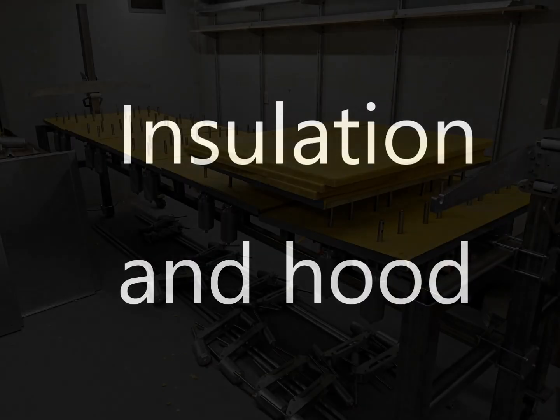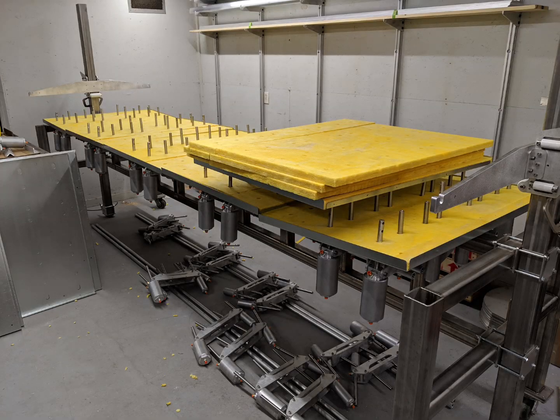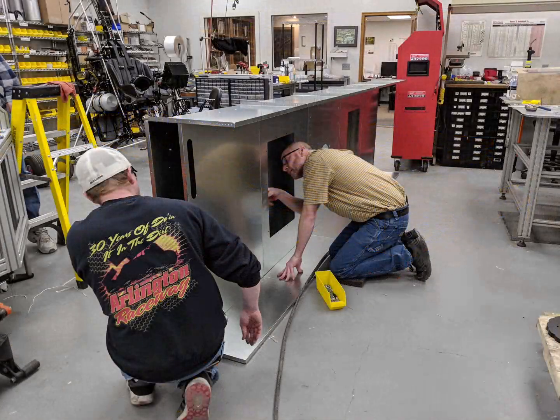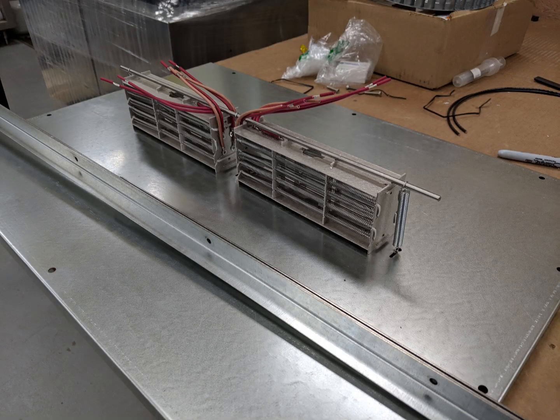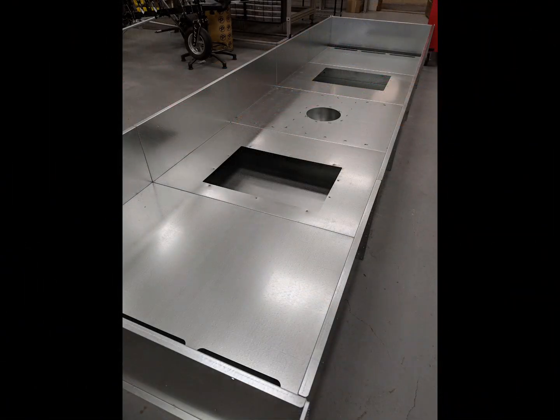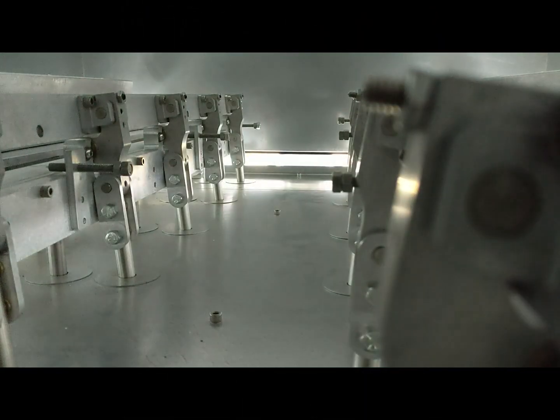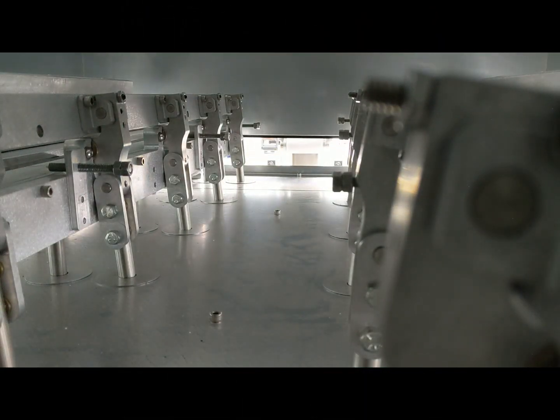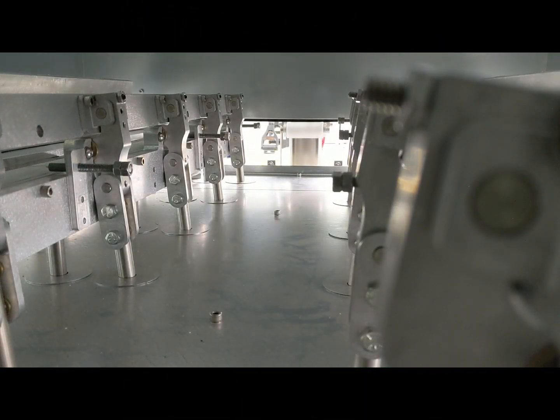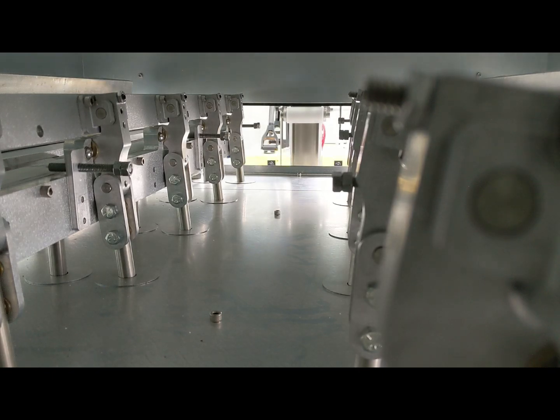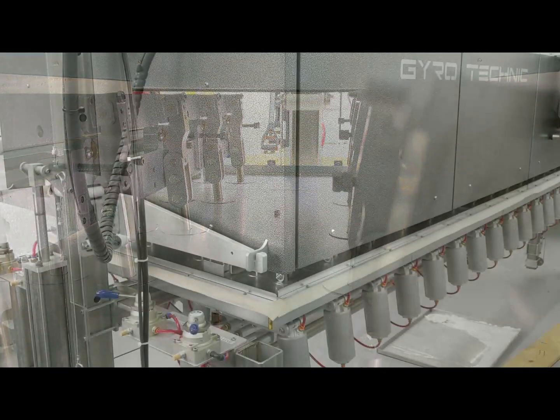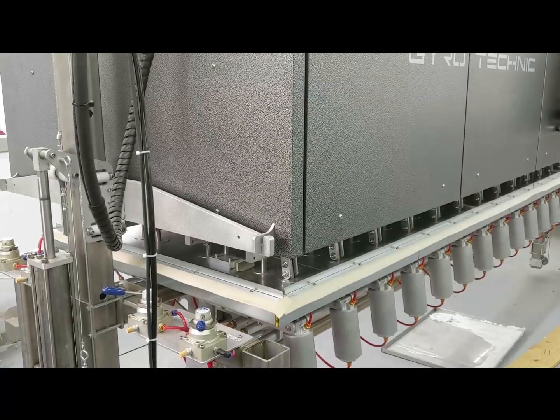The entire oven is well insulated to control the heat within. The hood of the oven is divided into 2 cavities. The upper cavity is for the heating elements and to keep them isolated from the product. This acts like a convection oven, with air being drawn up in the middle, passed through the heating elements, and then directed down on the ends with a constant air motion to heat all the components evenly. We're monitoring the temperature with temperature probes in 3 locations to assure accurate readings.